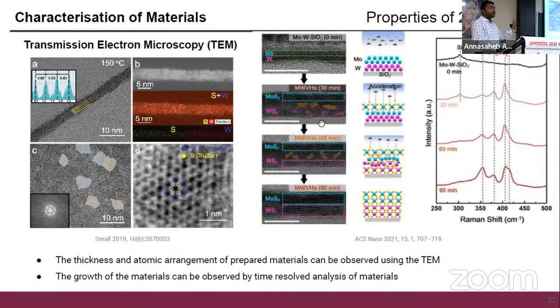Here is a time study of TEM, showing how synthesis takes place in plasma CVD. As I mentioned before, we deposit the metal layers. Here you can see there is no layer formation yet. But eventually, as you grow or sulfurize these metal layers, the size increases with layered formation. You can see the appearance of a few layers, or an amorphous nature, which then starts to rearrange and forms layered structures. Eventually, after full growth, you can literally see the full layer formation of these materials.